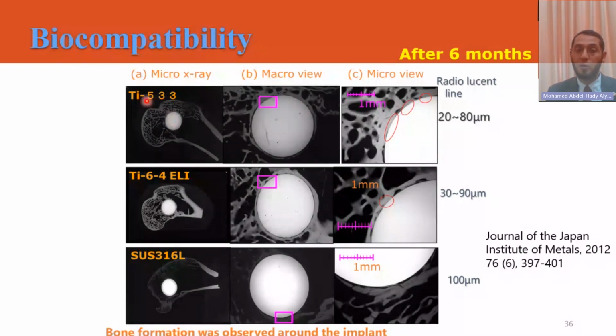If we compare our alloy, that's this one, which was successful, it's a 533 alloy, compared to the commercial, say, titanium 6, aluminum 4, vanadium, and stainless steel, that is a commercial one. We can see here our bone. Yeah, this is the implant, and this is the bone, new bone generated around the implant. We can see here, it's very nice. The bone grew around the implant very nicely, and the adhesion between the bone and the implant is much better than titanium 6-4. And you can see here the bone doesn't grow well around the stainless steel implant.